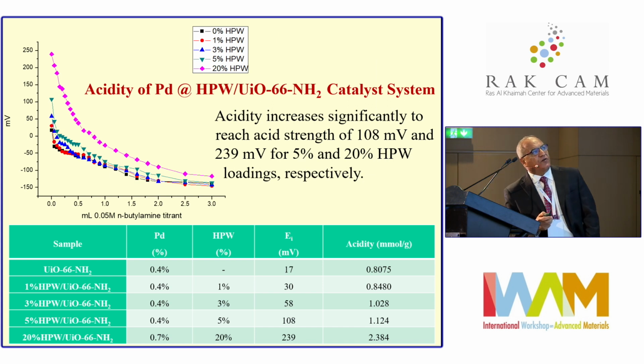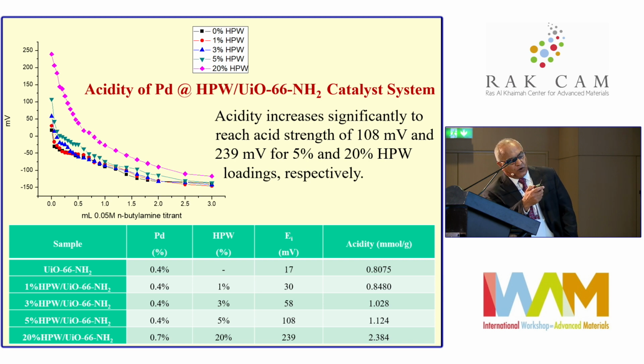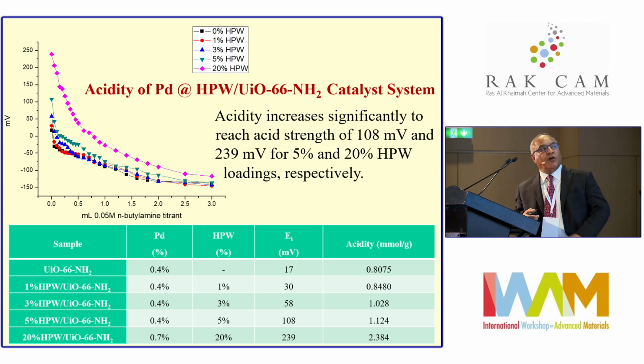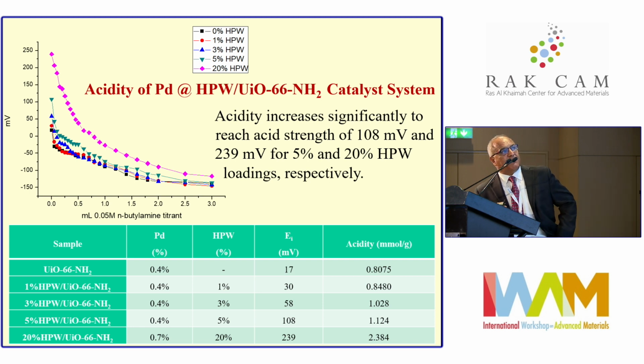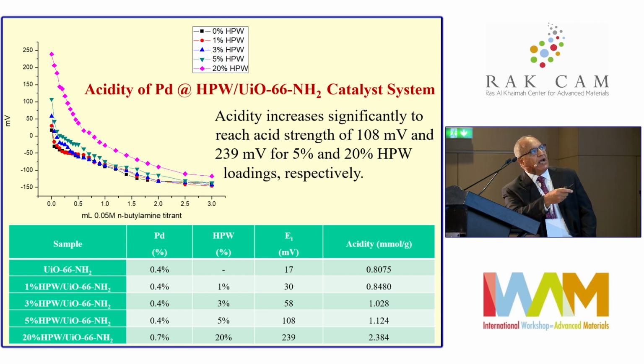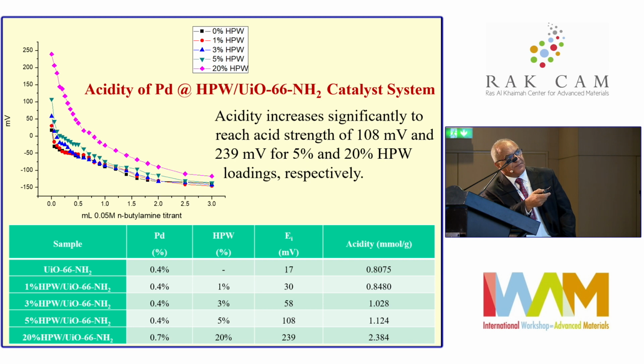We measure the acidity of these MOFs as a function of loading of HPW, and again, up to 5%, we can get increased acidity, which with 5% HPW within the MOF, we can measure acidity of up to 108 millivolt. But above that, if we go to 20%, we measure higher acidity, as you can see here. But of course, at 20%, we already have evidence of having the HPW outside the MOFs and leaching out of the MOFs. So that's not a good composition to use. We have to maintain the 5% loading.